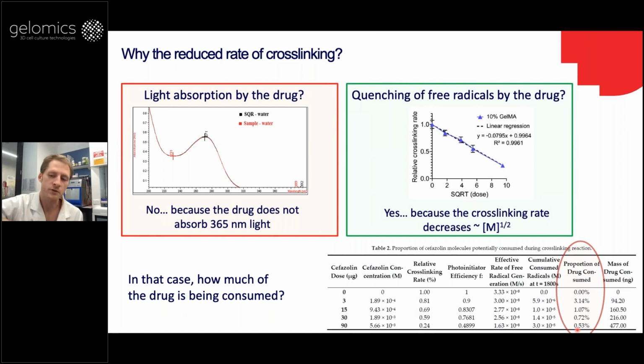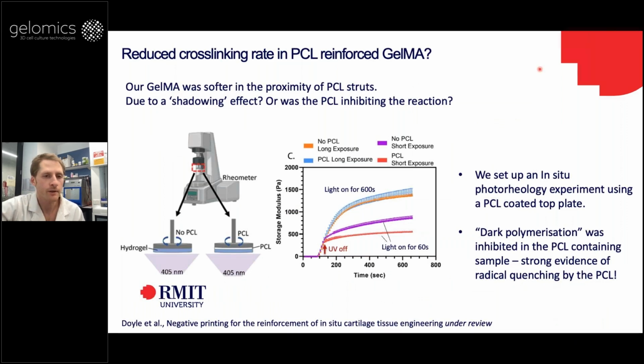So this is just an example to show that if you apply this quantitative approach based on kinetics, you can gain some insight into what's going on within your material as it's cross-linking, and help solve problems or explain results that you wouldn't otherwise be able to explain. And there's a lot of labs now that are loading growth factors into photocross-linkable hydrogels, or that are studying whether encapsulated cells affect cross-linking. So I think we should consider doing more in situ measurements to answer these kind of questions.